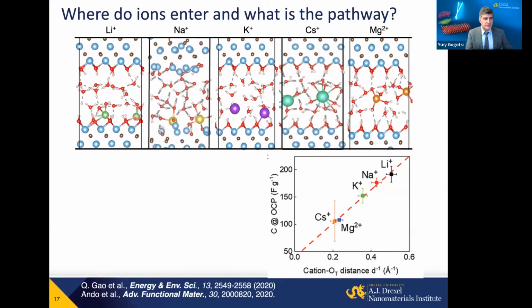Ions will also behave differently. Some ions, lithium and sodium, will be partially desolvated and may show specific adsorption, electrosorption on the surface of MXene, leading to larger charge transfer. Some ions, like for example, cesium or magnesium, will stay solvated in between layers and won't come close to the